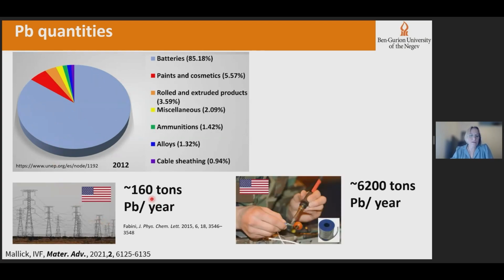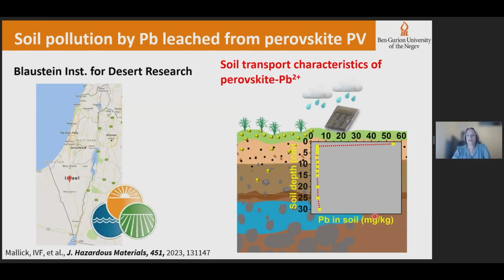If you calculate the amount of lead that you would need to provide the entire electricity needs of the US in 1 year using perovskite solar cells with 25% efficiency, which is the record efficiency, and 30-year stability, which is yet to be achieved, it would require about 160 tons of lead per year, which is a lot of lead, but it is still an order of magnitude less than the lead that is currently used per year in all other electronic utilities in the US in the same time. However, this is a concern, and in this research, we took advantage of our very interdisciplinary background